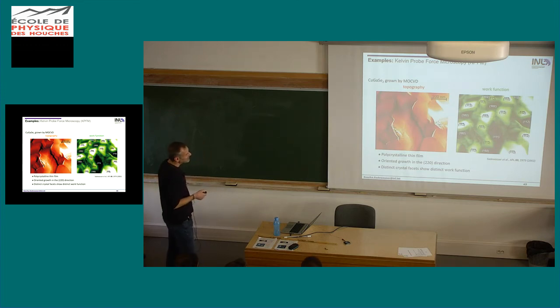And what we did is, because we also have three-dimensional information of our topography, we know from XRD measurements that the 220 direction is going out of the plane. So we can use the angles that we determine of our facets to that direction and to each other. We used this and compared it to tables for the crystal structure of the copper gallium diselenide, and we were able to index these facets here.